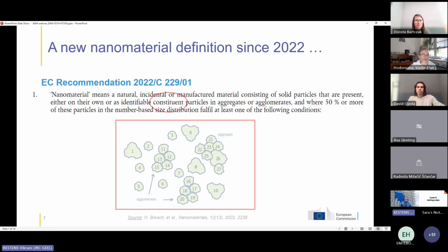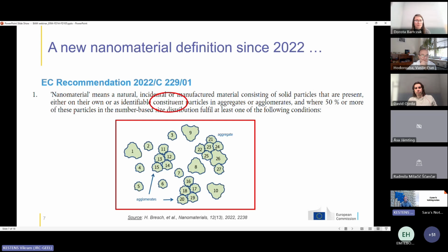And then a very important new term that has been introduced in that definition is the term constituent particles. This means basically that for the measurement of nanomaterials according to this new definition, you have to look at the constituent particles, or sometimes also referred to as the primary particles, within agglomerates and aggregates. And with that in mind, we developed two new certified reference materials, this ERM FD104 and ERM FD105, which have been characterized for the constituent particles.